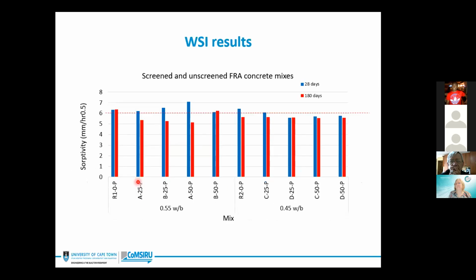For WSI results, we can see that all the concretes fall within good to excellent quality concrete, particularly the 0.45 mixes. Of course, we can attribute that to the denser microstructure and less porosity of these mixes. Results also show that prolonged curing is beneficial to the 0.55 mixes.